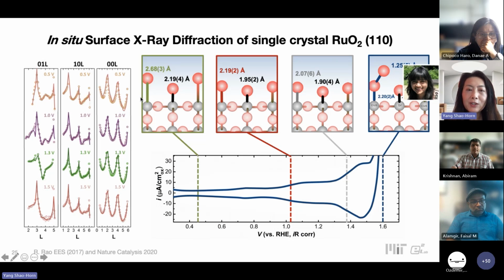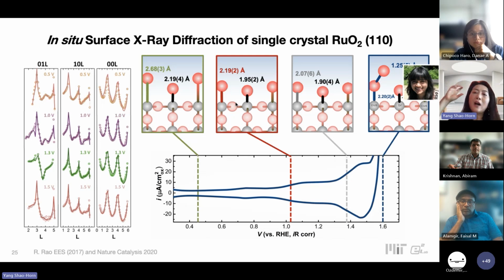So if we have such a surface, typically we have two sites. We have a ruthenium cusp site and a bridge site. As the cusp site adsorbs water and we increase the voltage, the water can gradually be oxidized or deprotonated from water to OH to O, and at oxygen evolution potentials becomes a superoxide species. This is something we can directly detect, probe and refine through the in situ surface X-ray diffraction measurements. We see the reduction of the distance of the oxygen getting closer to the cusp site. On the other hand, for the bridge site, the distance doesn't change very much, and we see the site is oxygen terminated. From such measurements, we can see the cusp is the active site, whereas the bridge is not involved in the catalytic activity of oxygen evolution.